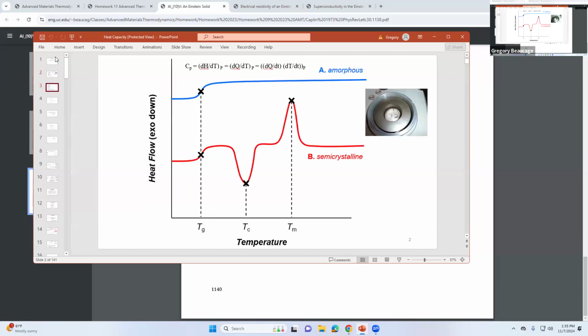The semester is spinning by, you know, and that's a picture of a DSC measurement. So you see that in the characterization class, right? That's the DSC. This is actually a polymer curve, with a glass transition. This would be like a water bottle, PET. It's clear, non-crystalline when you have it, because it's been extruded quickly and cooled. Then when you heat it up, you go through the glass transition.